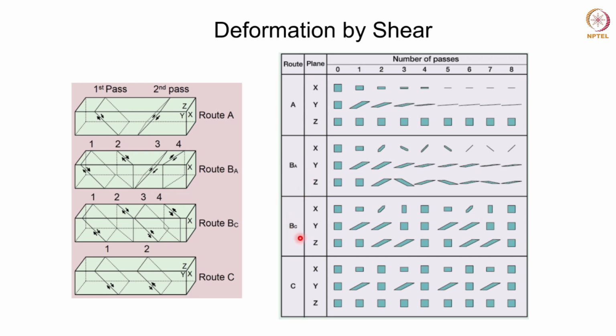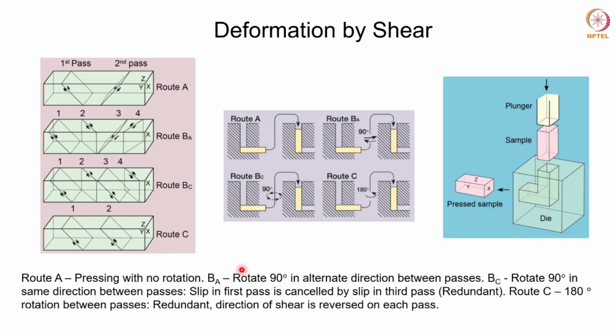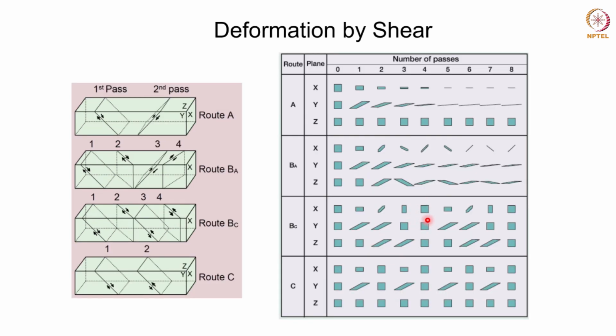In route BC, on the other hand, it is rotation in the same direction by 90 degrees between passes, right? So here first it is deformed, and then it is rotated 90 degrees, another 90 degrees, and then another 90 degrees. So when you come to the fourth pass, you can see that the element is restored again. So this is what I said before. If you remember, in case of route BC, the slip in the first pass is cancelled by the slip in the third pass, and therefore in the fourth pass it will be back to the original condition, right?